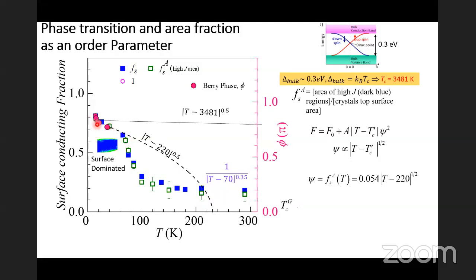If you look at the blue data points, the surface conducting fraction, which is measuring the surface dominated conductivity from the topological surface state, we wanted to analyze this in terms of the electrons present inside the system. So one is the 2D surface state electrons, the Dirac electrons. But above a temperature which is the bulk gap temperature, about 0.3 eV, you will also have normal electrons generated because of excitation above the gap. So above a temperature Tc of about 3000 Kelvin, you will get a dominance of normal electrons over the Dirac surface electrons.